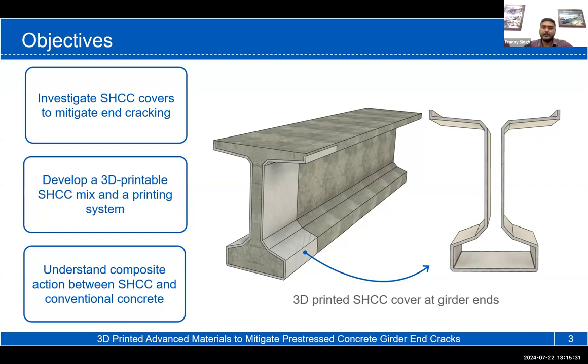Yes, so regarding that, to control these cracks, there are various methods. The first one is the enhanced reinforcement at the ends. So we can do that. The second one is using better mix, like using fiber reinforced concrete or ultra high performance concrete for the entire ends. So these are some of the methods, and there is literature on them. People have used that, but those methods still have some problems. Even with fulfilling all those criteria of reinforcement at the end zone, people have observed the cracks. Applying the fiber reinforced concrete for the entire girder will be expensive as well as difficult to do, because first of all, handling the fiber reinforced concrete is more difficult than conventional concrete. It is expensive. And if we want to just make the end zone with those fiber reinforced concrete, then having a separation for pouring or implementation stage is difficult. So for those reasons, we are considering this kind of solution.